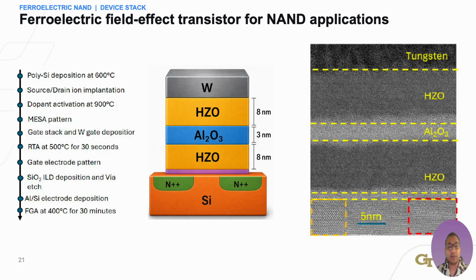We first built a ferroelectric field effect transistor with a silicon channel as a control test platform. The active gate stack consists of two ferroelectric hafnium zirconium oxide layers sandwiching an aluminum oxide insert. The process includes source drain implantation, ferroelectric thin film deposition using the atomic layer deposition technique, rapid thermal annealing, and back-end contacts. The cross-sectional microscopy confirms that the laminated stack and its interfaces are physically realized at the intended nanometer dimension. This test structure lets us optimize the gate stack.